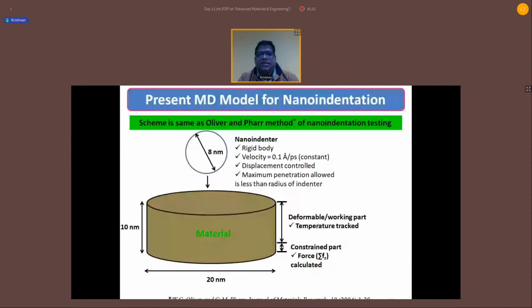That method is very early. It was discovered in 1992 by Oliver and Pharr, and we are using a rigid indenter here. The beauty of the rigid indenter is that there is no interaction between the indenter and the surface, so we do not consider the interaction between the surface and the indenter. It only indents the surface, and after the localized indentation, we can calculate the property using Pmax, the maximum load, divided by area.